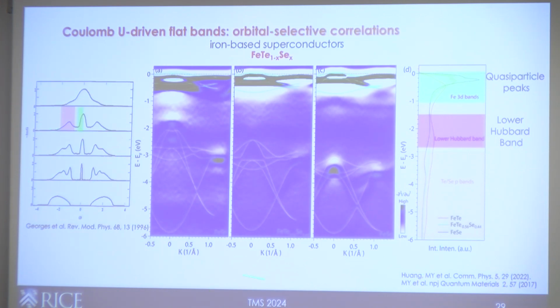And so if you take one of these moderately correlated materials and take a large energy range ARPES map, a lot of stuff happens, but if you integrate along this dimension, which is shown here, you will see essentially a measure of the density of states. You've got all these quasi-particle peaks close to the Fermi level. And then if you go higher up, around 2 eV, there's the hump. Sorry, I don't know if it's showing up on the screen, but you can see a band here. That's the lower Hubbard band, essentially similar to this stuff here, right? So you can actually directly see this with photoemission.